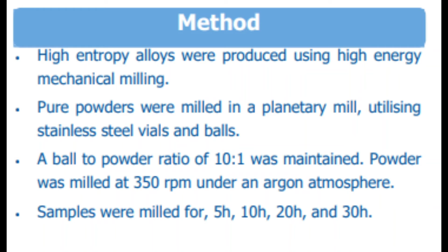The pure powders were milled in a planetary mill at 350 rpm under an argon atmosphere to prevent excess oxidation that could have been dangerous. Stainless steel ball bearings as well as vials were used, and a ball to powder ratio of 10:1 was maintained. The samples were milled for 5 hours, 10 hours, 20 hours, and 30 hours. This would allow us to see at what time the high entropy alloys were formed, and therefore had the smallest amount of time possible to forming these high entropy alloys.